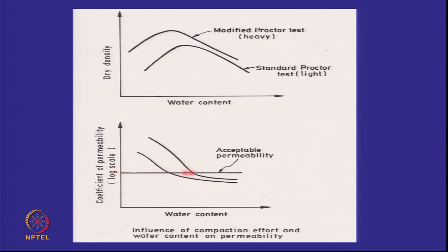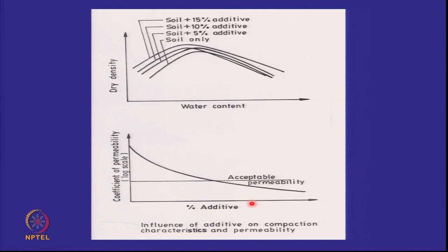If this is 10 to the power of minus 7, I know that I should compact wet of this point to get that permeability. When I'm using an additive, my compaction curve will change with the amount of additive. So I cannot predict how it will change, but I can get these different curves. And then for each curve at a given prescribed water content wet of the optimum, I can find the permeabilities and I can get a plot of coefficient of permeability with the percentage additive that I have added. And again, this will give me how much additive is required for getting the permeability.